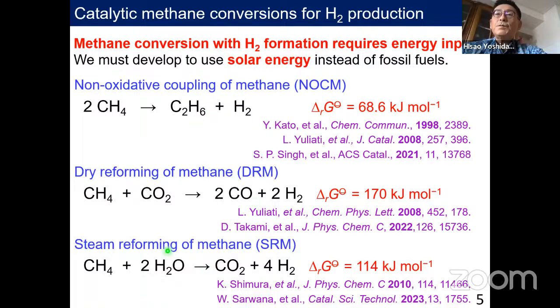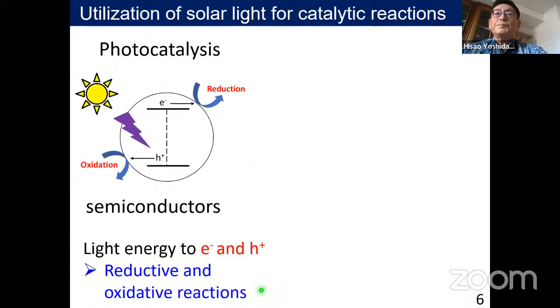And these kinds of reactions need a huge energy to go to the products. Here, I show the Gibbs energy of these reactions. These values are very high to operate at room temperature, so we usually need high temperature to operate them. But we studied by using the photocatalyst for these reactions, and we succeeded to promote the reaction. Unfortunately, the reaction rate is still low, but we are trying to increase it.